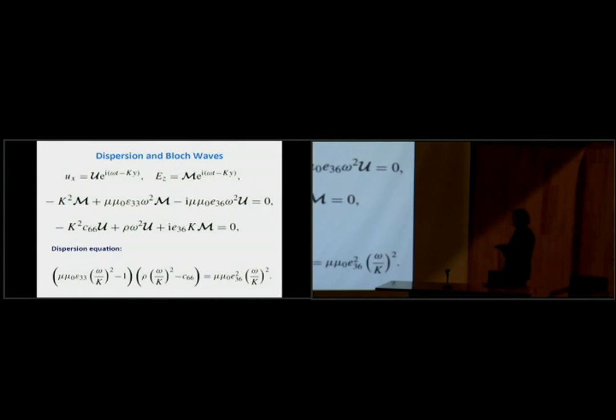then if you look for so-called Bloch waves, which are the waves that satisfy this relation, then you can see that for the amplitudes U and M, you can write this very simple system of equations. And it's a homogeneous system, and of course, you would like to have a non-trivial solution, and the solvability condition for this system gives you the dispersion equation. So you can see that, yes, indeed, there is dispersion, there is coupling between electric and elastic waves, but if you take the numerical value for this coefficient, you can see that it's very, very small. So in practical terms,